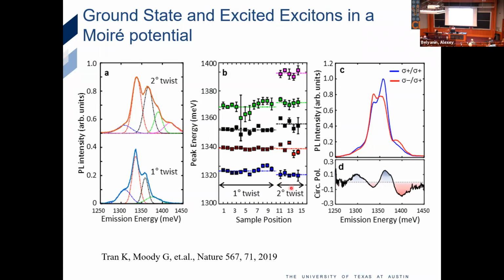But you start to see with the 2 degree sample, the energy spacing appears to be larger. If you allow me to use the simplest quantum box model, you make the box smaller, you learn in quantum mechanics, you make the energy spacing bigger. It's a very simple picture to explain this spectrum. And very peculiarly, in the 1 degree sample, we use sigma plus to pump the K valley, for example, and then you see the emission has an alternating selection. That suggested to us that it is related to the Moiré. That's another piece of evidence suggesting this is related to Moiré energy modulation.